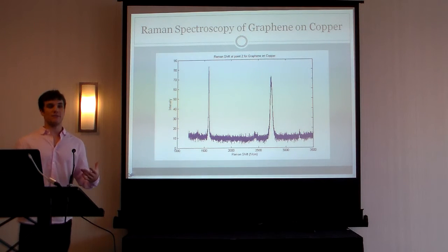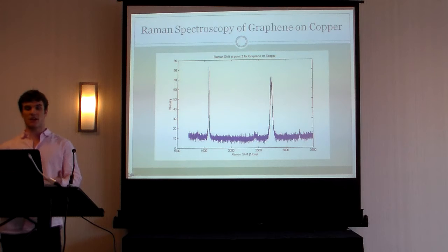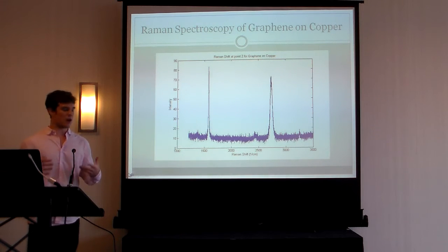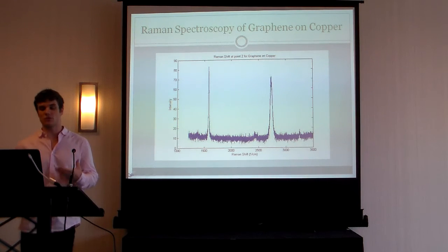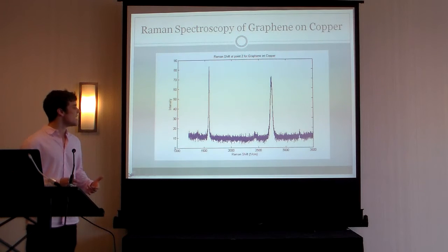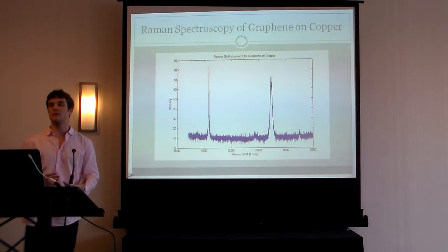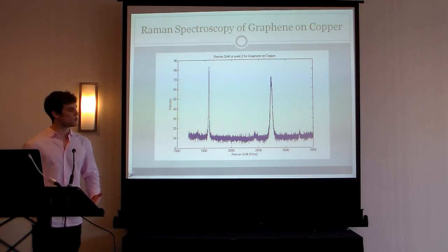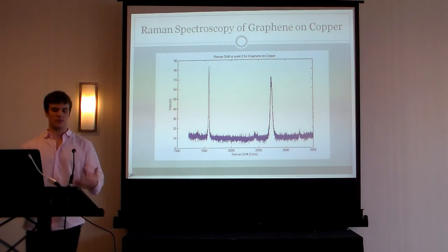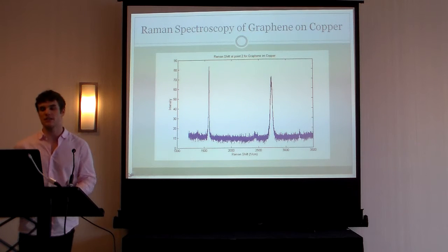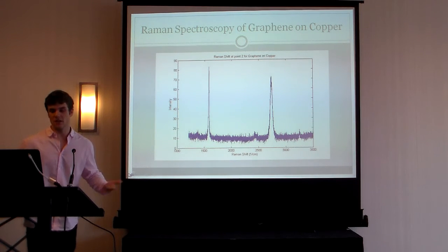There are defects that can be introduced, like heptagon and pentagon defects, which are somewhat resistive, as well as grain boundaries, which are highly resistive. And knowing the height of this defect band while doing transfer of your samples will allow you to know more about your system when you go to characterize it using other techniques.